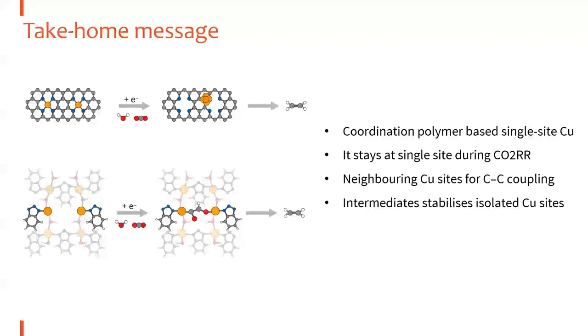And the copper aggregation is actually the real active site for this reaction. But what we have done is that we have developed a new coordination polymer with single site copper, and it remains stable during CO2 reduction. And the reason why this single site copper can form C2 product is that we have neighboring copper sites with suitable distance, and the CO and the CHO intermediate can couple together to form the final C2 product.